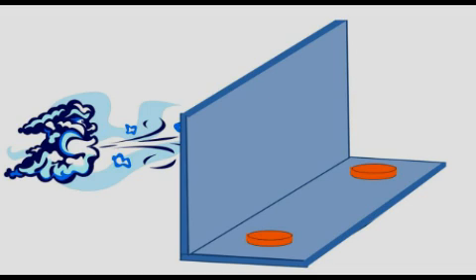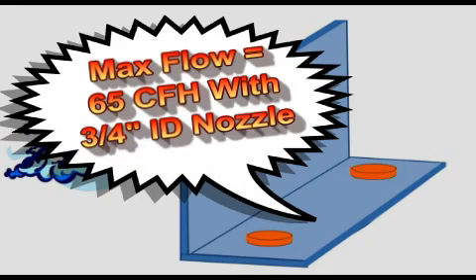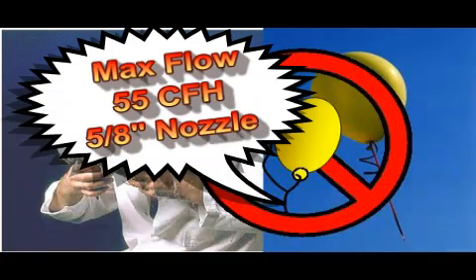A simple windshield can also be made from sheet metal and moved as welding progresses. A larger 3/4 inch ID nozzle allows increased shielding gas flow up to a maximum of 65 CFH, but no higher. Unfortunately, some folks believe if some is good, more must be better when it comes to setting shielding gas flow. We often see flow meters with a ball pinned to the top of the flow gauge, and we have measured flow rates of 125 to 150 CFH at the gun nozzle when needle valves are fully opened — that is far too high for good shielding.